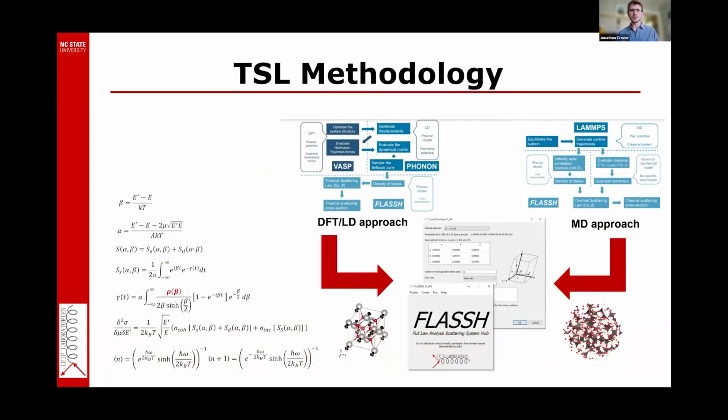Generally, what we do with TSLs is you can have a DFT approach or an MD approach, if anyone's familiar with these techniques. With the first principles approach, the point is to produce a very high fidelity, accurate description of the phonons in the crystal structure. So we use DFT and MD to produce a phonon distribution, or a density of states. That is the kernel and the nugget of the fundamental physics, which we can use in FLASSH.